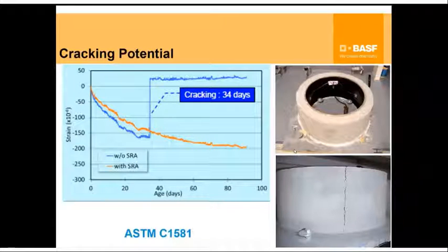For the other concrete, which has shrinkage reducing agent in there, the crack has not happened, mainly because the stress buildup is being mitigated by the shrinkage reducing agent. Next.